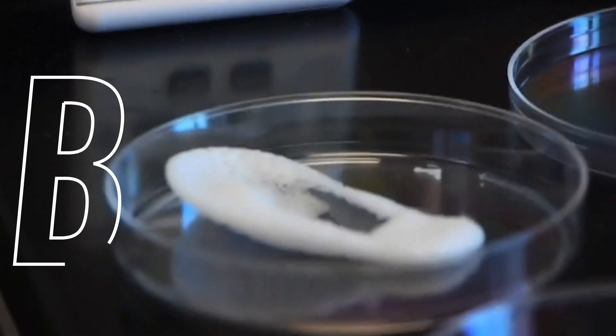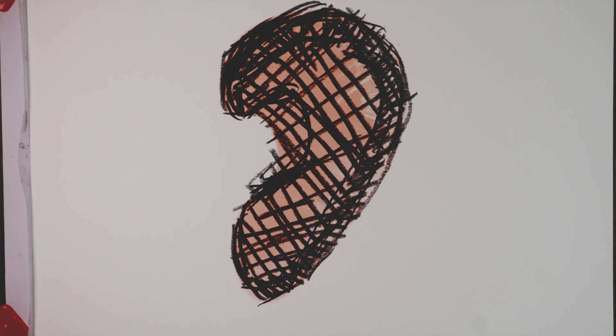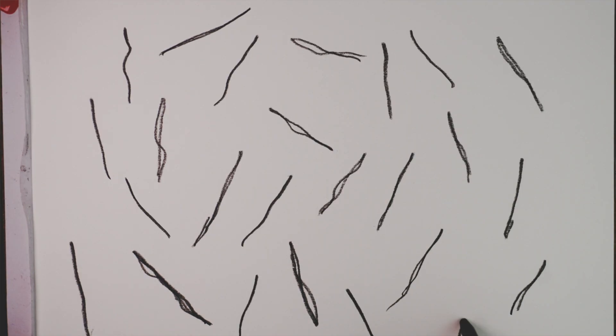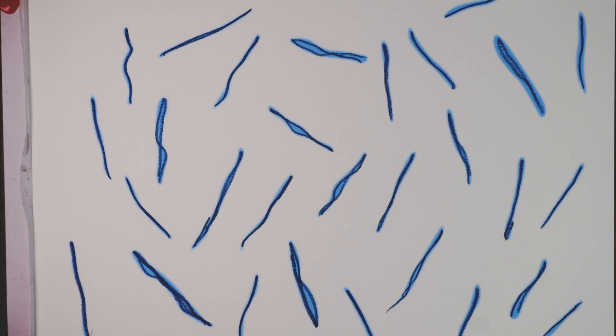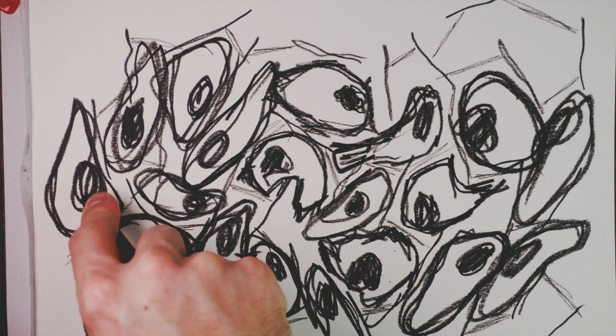One major difficulty with printing living material in 3D is to make the 3D structure maintain its shape while providing a suitable environment for the cells to grow in. The key to solving this problem is to find an appropriate bio-ink. Bio-ink is the material used to print tissue and is made of cells, biological polymers, and man-made polymers suitable for interacting with living material. The stiffer the bio-ink is made with the polymers, the better the printed tissue can hold its shape. But if we make the liquid too stiff, it's hard to mix cells into the material and cells won't grow in the printed constructs. Cells need a watery and soft environment to thrive. A trick many bio-inks use is to cross-link the polymers after printing to create a firm network — making the ink liquid enough for printing and then solid enough for creating a desired shape while providing cells a suitable environment to live.